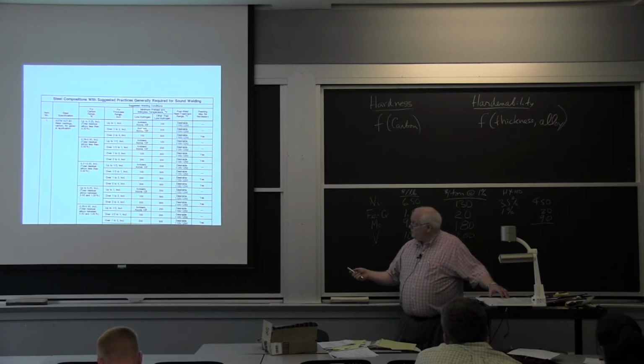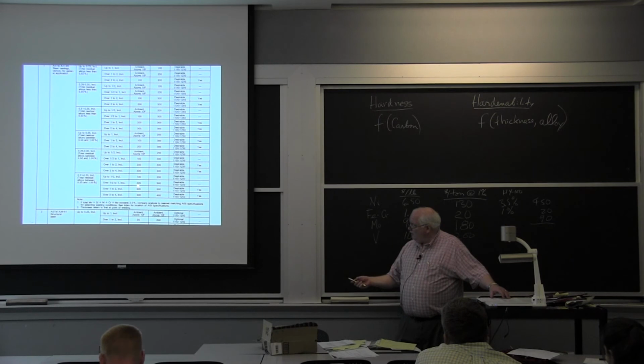But ambient, basically, if I come down here with alloy content, even with higher carbon, I got to have at least 100 degree preheat, and if I don't have low hydrogen, and if I'm very thick, it might be 400 degree preheat. When we redid the Seawolf, they were doing 400 degree preheat.